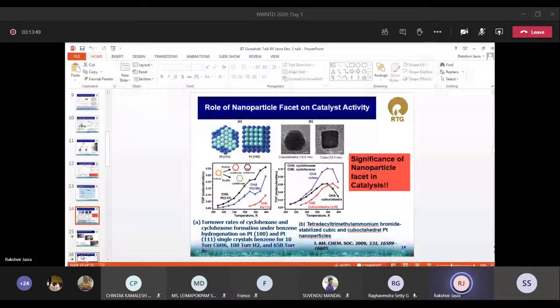When I do benzene hydrogenation, you will get cyclohexane as well as cyclohexene. But if I use this platinum 100 facet rich material, then it is a complete hydrogenation. You don't get cyclohexene. Now, when I am doing hydrogenation of benzene, formation of cyclohexane is very important. If I can make cyclohexane selectively, I can really add good value to that product, because it is further used for making some products. So this type of information is also very, very valuable.